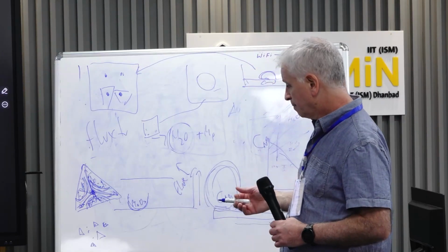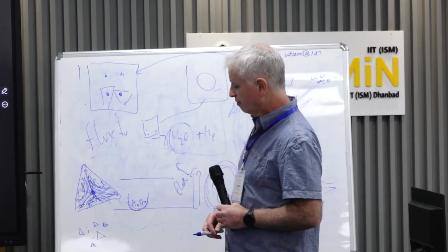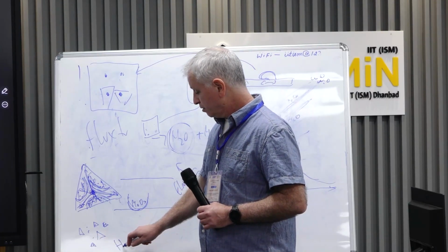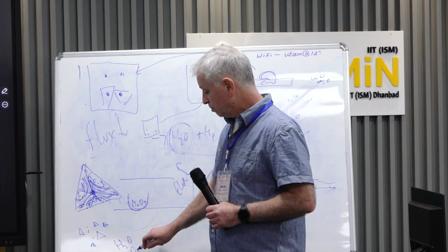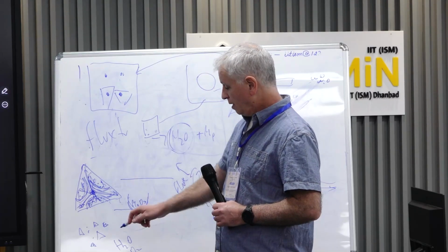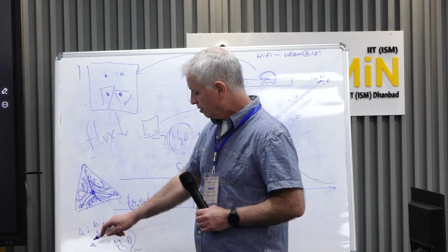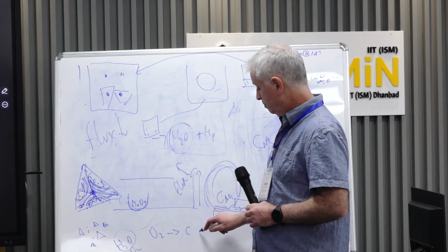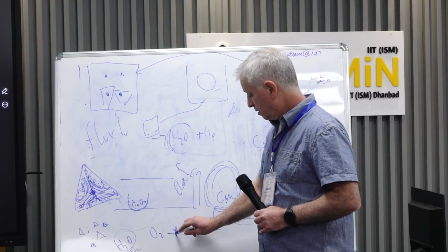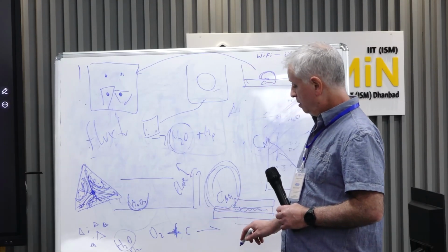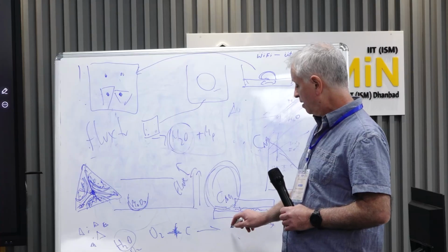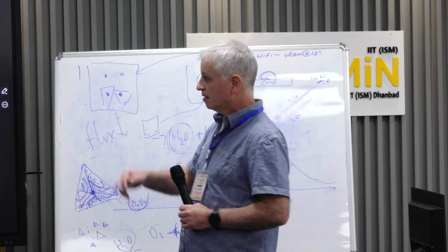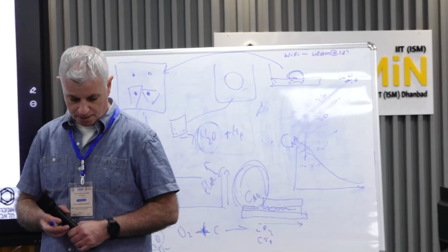All these we'd like to get rid of, and that's what we did by introducing H2 or O2. Because again, the oxygen will react with the carbon to leave CO2 and CO, both gases that are easily exhausted.